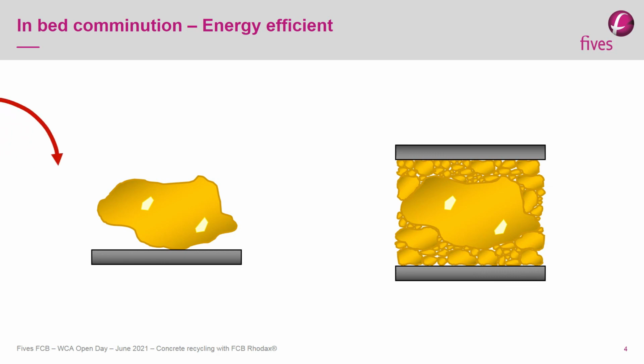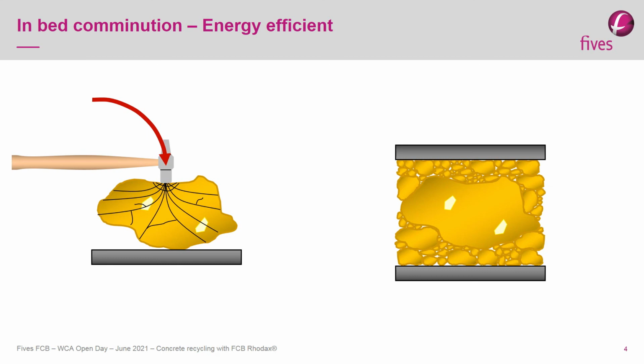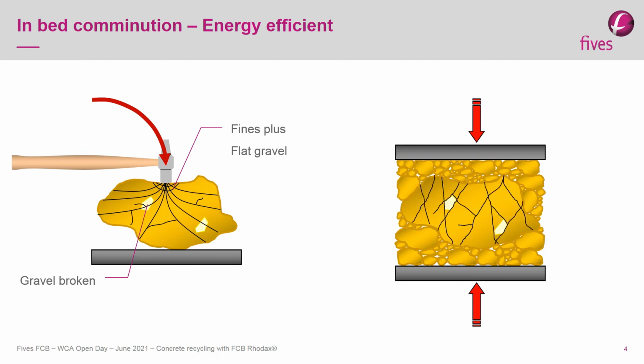On the left-hand side, you have a figure of what happens in impact crushing. And on the right-hand side, you have the figure of what happens in compression grinding. Rhodax is an interparticle crusher that works in bed comminution, like FCB roller mill, vertical roller mill, and HPGR. Benefits in concrete application are to liberate the gravels from the mortar matrix and to get a very good particle shape. Also, the quantity of ultrafines generated can be controlled.